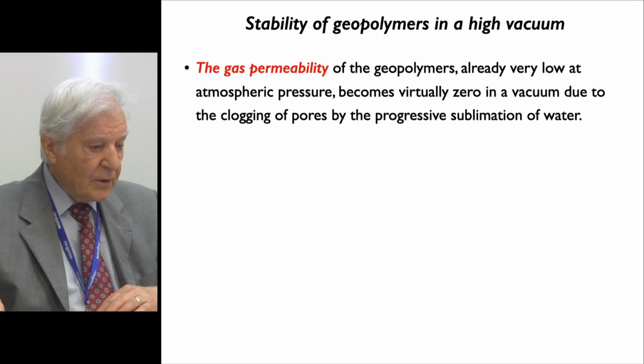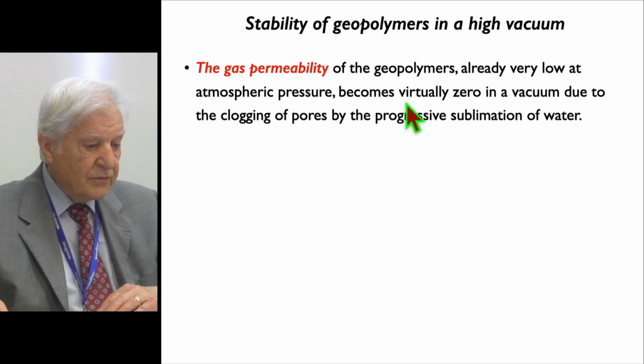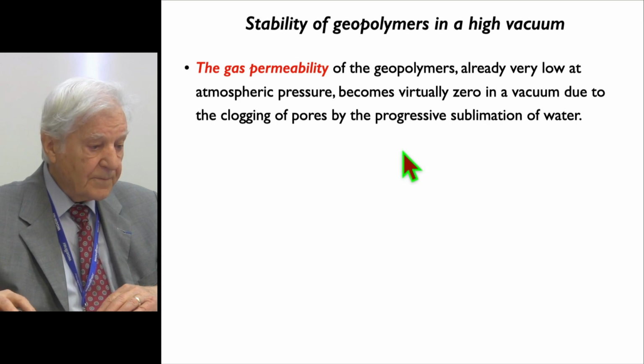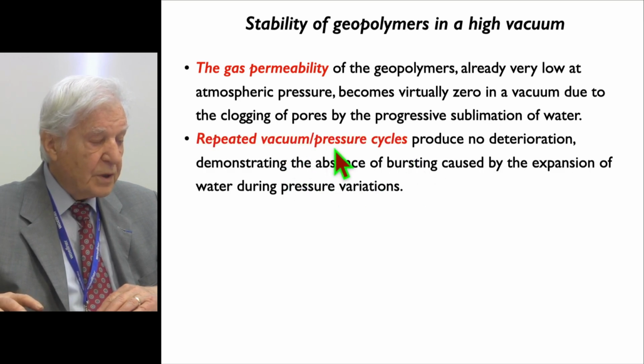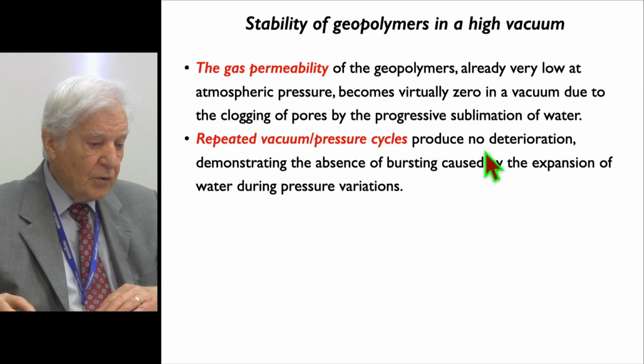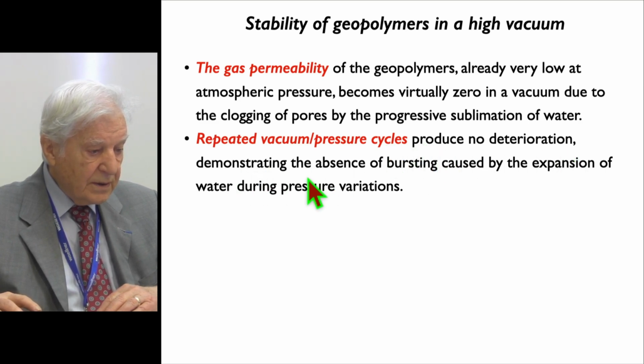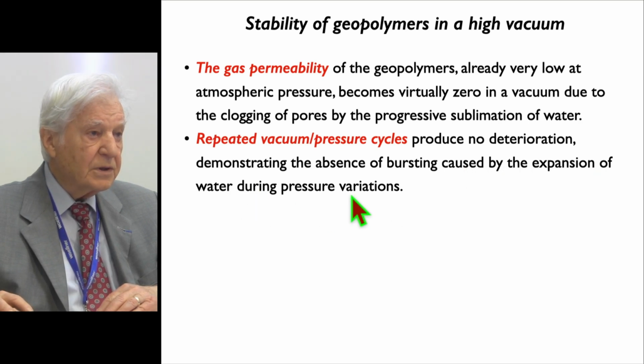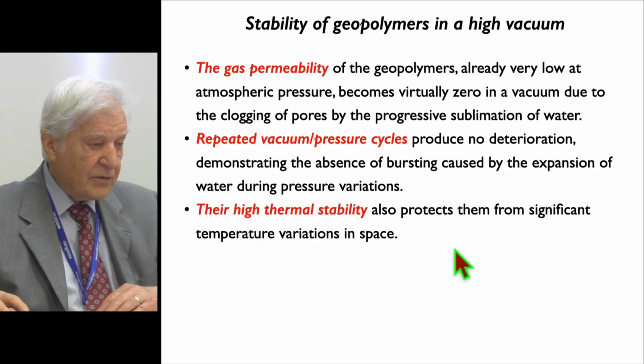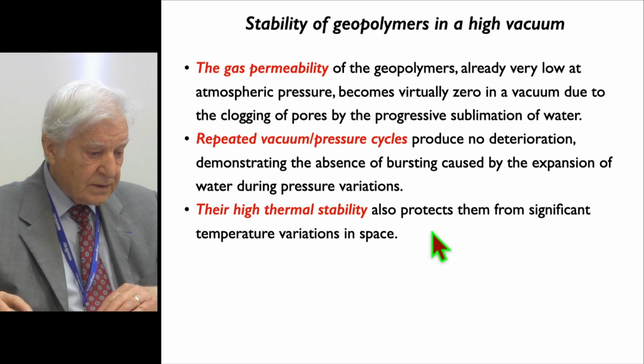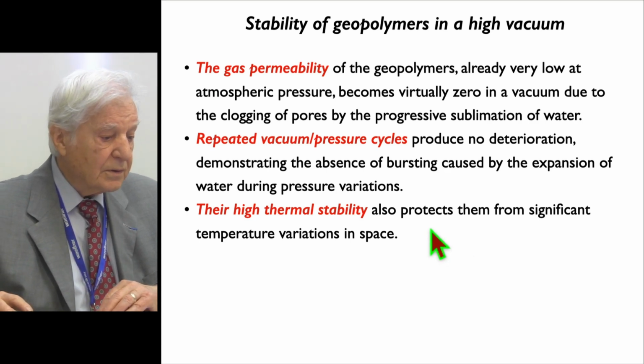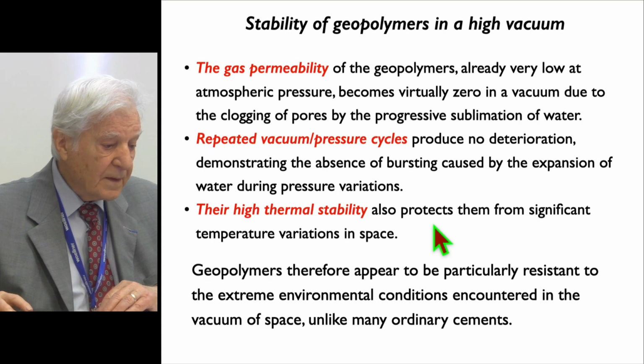Gas permeability of the geopolymers, already very low at atmospheric pressure, becomes virtually zero in a vacuum due to the clogging of pores by the progressive sublimation of water. Repeated vacuum pressure cycles produced no deterioration, demonstrating the absence of bursting caused by the expansion of water during pressure variations. Their high thermal stability also protects them from significant temperature variations in space.